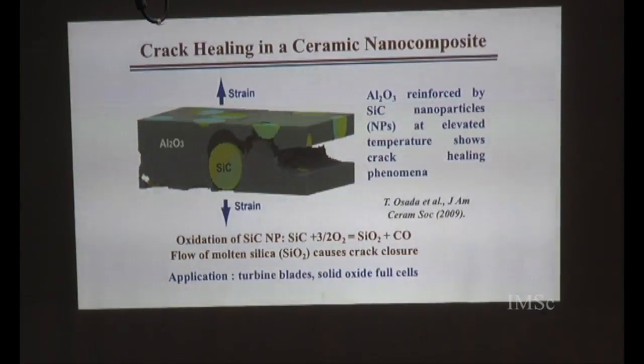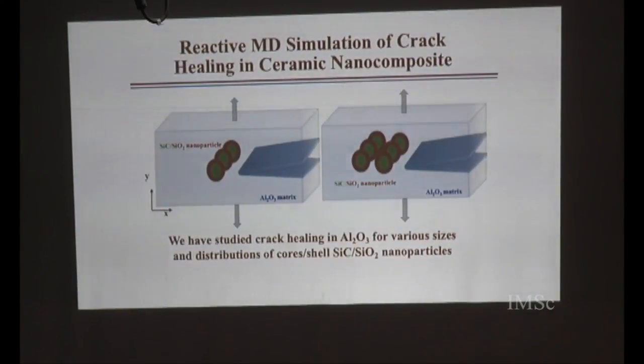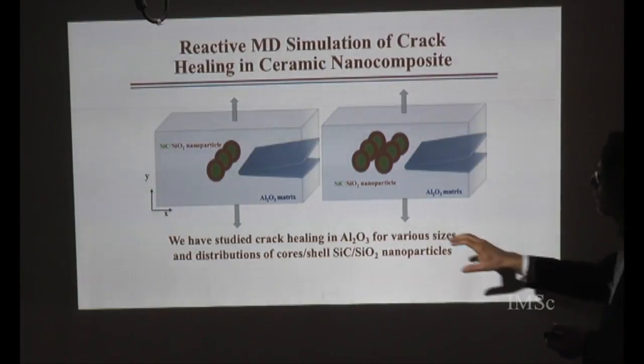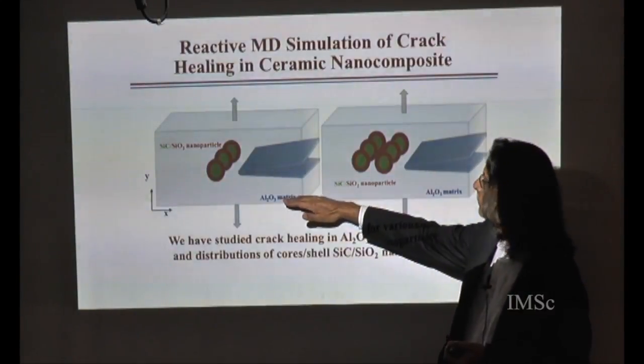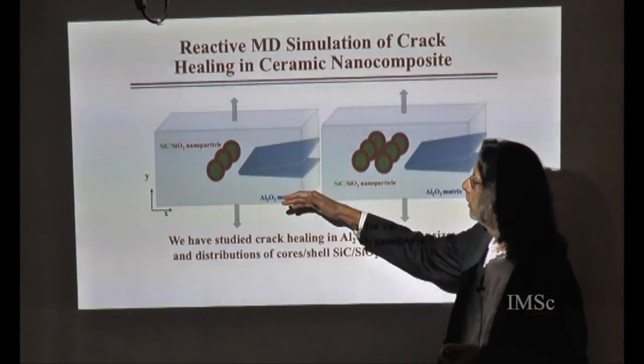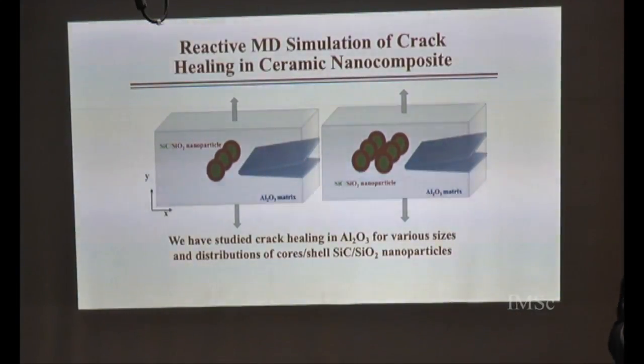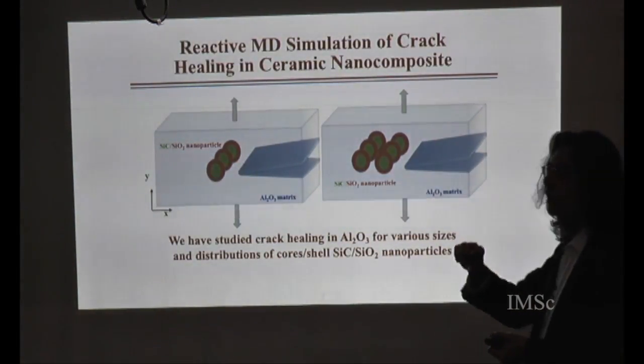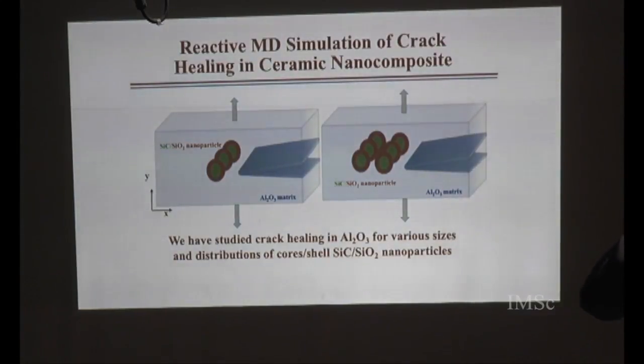So as you can see, there are several applications of these things. The system we have simulated, these are reactive simulations, so all bond breaking and so on are correctly described. So what we have is an alumina matrix. It is pre-cracked, and in front of that, you have a row of nanoparticles. These nanoparticles are silicon carbide with an oxide layer, so a silica layer on top of silicon carbide.